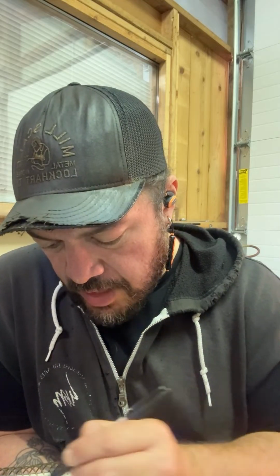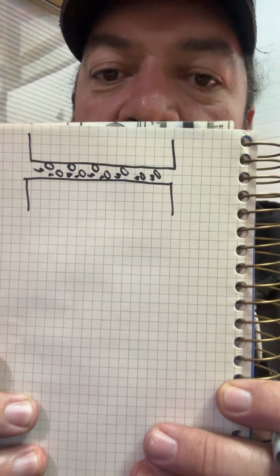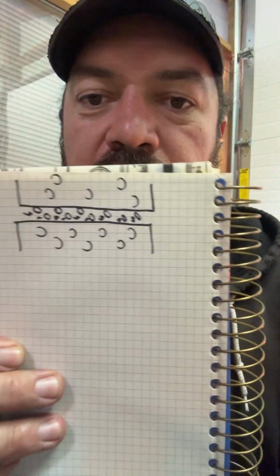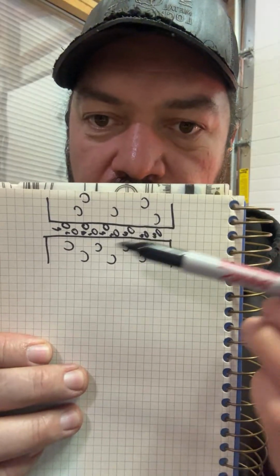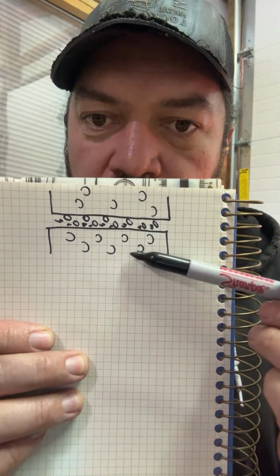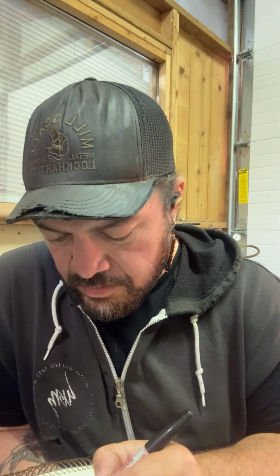You got all this oxygen. You got all that oxygen in there, right? In between your layers. And then as the steel starts heating up, sorry, let me back up. So this is what it looks like before you put it in the forge, and when you initially put it in the forge, you have all this oxygen in between, you have this carbon. But what happens as the steel heats up, the carbon starts moving all over the place. Right? Carbon moving all over the place.